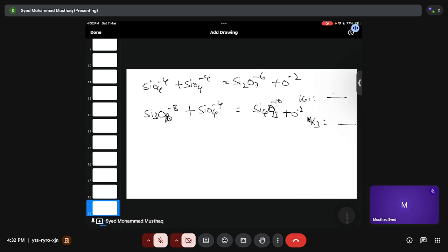From Mason theory, the main assumption is that if I keep on adding silica, I will have more equilibrium constants coming, right? So these are all equal to one value K. That means they are all equal. That means every K value can be represented in terms of this one. Why? Because every time we are trying to involve silica, and whatever the product is again acts as a reactant for the next reaction. So I can generate an empirical formula.